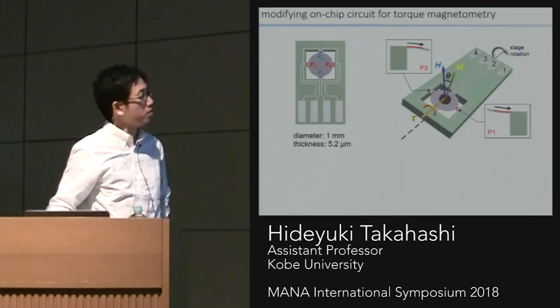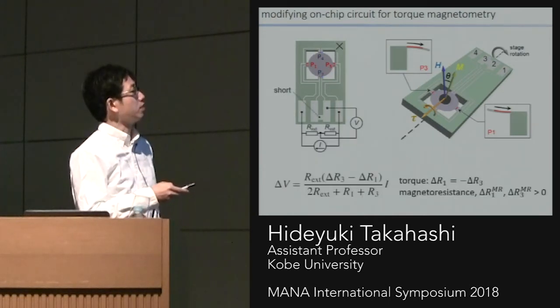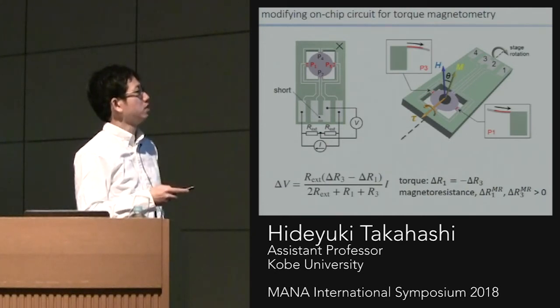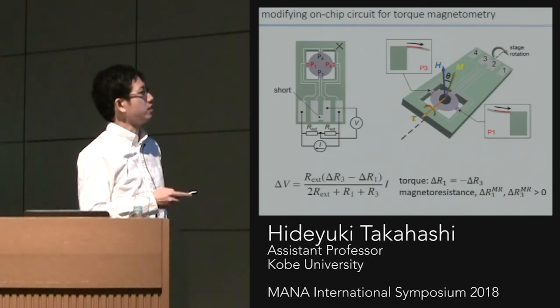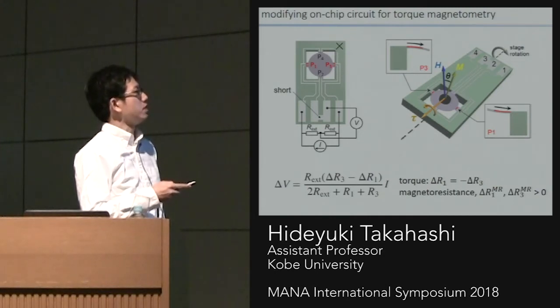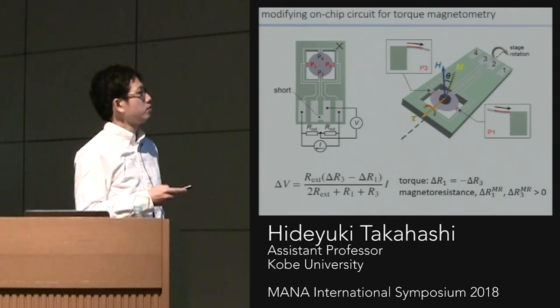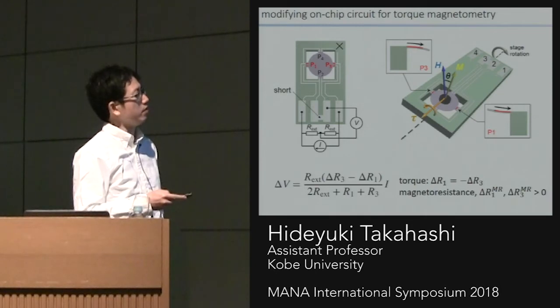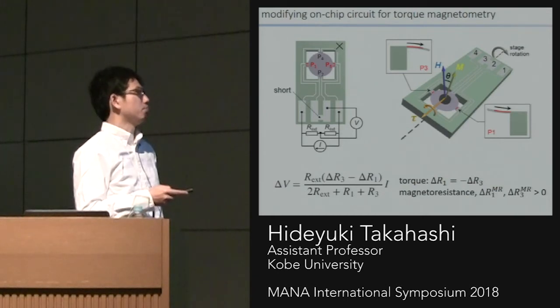But in this measurement, we use only P1 and P3, and P2 and P4 become inactive after we remove the wire here and short the path here. By doing this, we can push the electric current through only P1 and P3. P2 and P4 become inactive in this configuration, but this is not a problem because P2 and P4 are on this symmetrical line, the stage rotation axis. So we detect the twisting motion of the membrane caused by magnetic torque using these two piezoresistors.